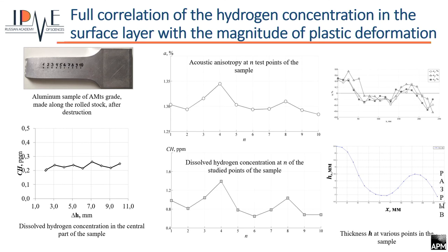And during the plastic deformation, there is also formed a very thin surface layer, and the mechanical properties of all the samples are determined by the properties of this surface layer. For example, in this layer, we can see the hydrogen accumulation, the hydrogen from atmosphere. In this layer, we can see residual stress accumulation. And in this thin layer, we can see also damage accumulation that leads to acoustic anisotropy changing, acoustic anisotropy signal change.